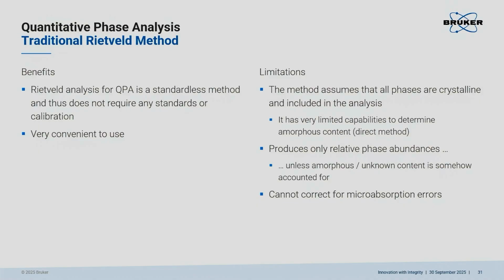Now, the Rietveld analysis is very popular because it is a standardless method, and it is extremely convenient to use. And what happens is people use it indiscriminately. I would say 90–95% of all people doing quantitative phase analysis use the Rietveld method, although there may be many other methods which are much, much more suitable for the sample at hand. Now, the Rietveld method, always keep that in mind, the traditional Rietveld method assumes that all phases are crystalline and are included into the analysis.